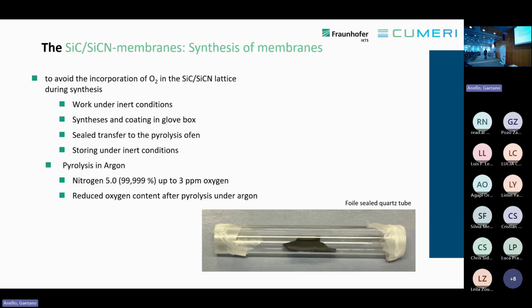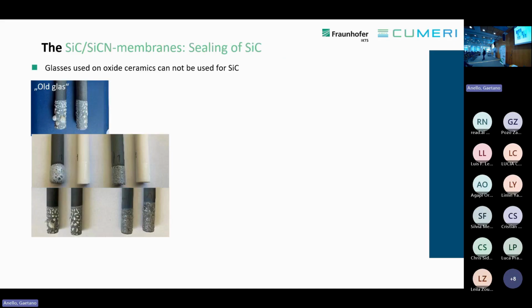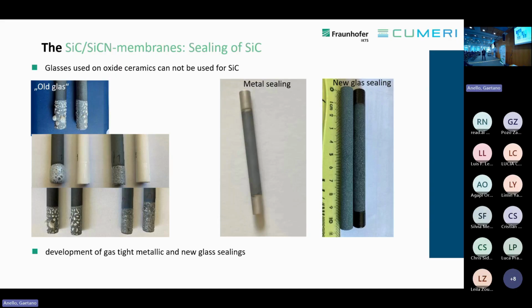However, we have done all this and it works more or less. Then we had another problem we hadn't had in mind before. If you are coating membranes inside of a tube, you need an end sealing for the membranes. However, the glass we typically use on our alumina tubes does not work in combination with silicon carbide. You get gassing of the glass and bubbles, so you cannot use it. This needs, of course, a lot of time to develop alternatives. We developed two alternatives: a metal sealing and also a new glass sealing, and both are gas tight, which is very nice.